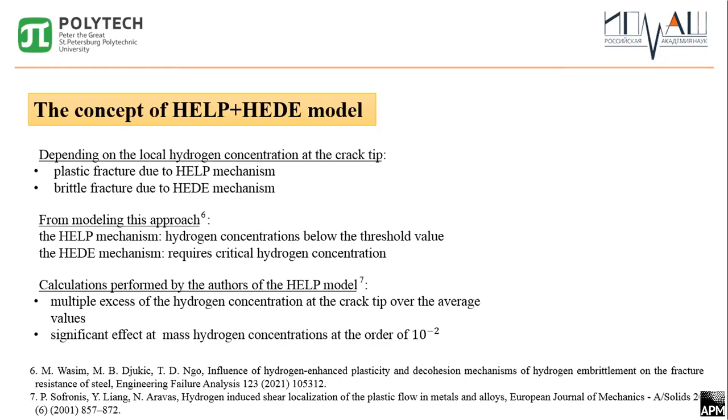According to this concept, the fracture mechanism was determined by the local hydrogen concentration at the crack tip. In work devoted to this hybrid model, it was shown that the HELP mechanism works at hydrogen concentration below the threshold value, while the activation of the HEDE mechanism requires reaching a critical concentration. But these works were based only on the analysis of the microstructural fracture surface. Direct measurements of the hydrogen concentration distribution have not been carried out.